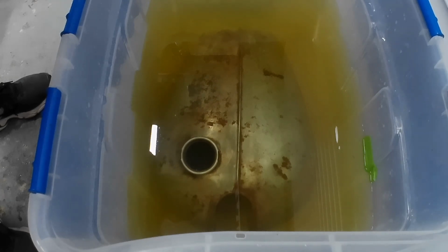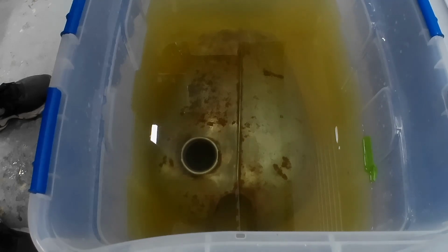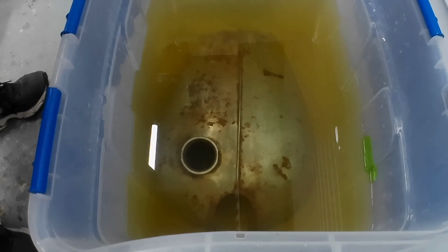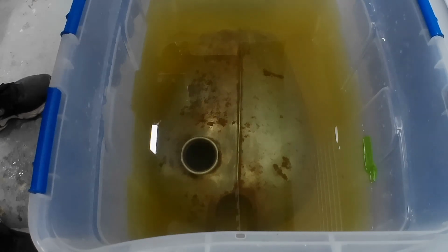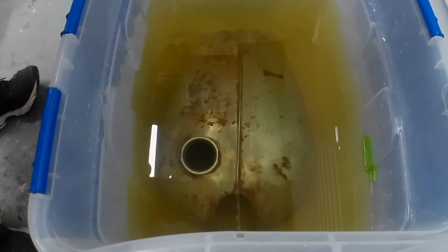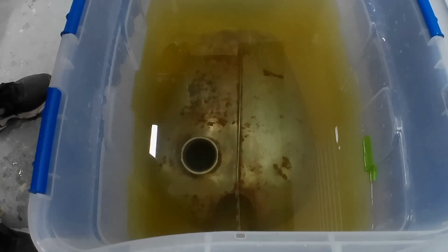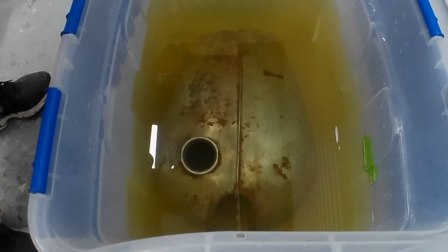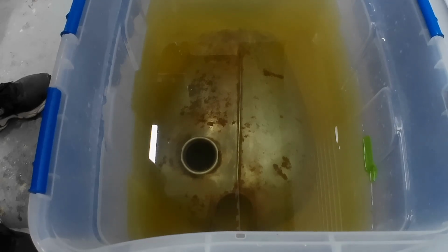In fact, when I did the D7 tank, I didn't immerse the whole tank. I just filled the tank up with this stuff once I'd cleaned it. And it completely removed the rust, and it did leave a slightly etched surface, which was perfect to allow the resin sealer to key. So to some degree, it's an advantage, but obviously you don't want it to get out of hand. And again, a slightly etched surface on the outside of this tank won't really matter because it's pretty pitted anyway from the rust. So, the lesser of two evils.